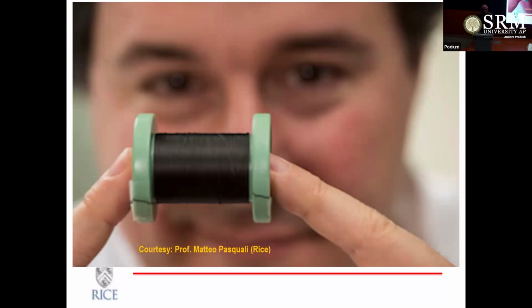So the only issue with carbon nanotube is it's too tiny, right? It's about 1 or 2 nanometers in diameter and maybe microns long. But you can't really use a nanotube that is a few microns long as a fiber for any practical applications. So in order to get to that point where you can actually use these nanotube building blocks as a fiber, you need to put them together. You need to engineer them into a real fiber that you can practically use, like a carbon fiber. Now, it has taken almost 30 years, and we still don't have a fiber that is as good as the present carbon fiber, which is made by extrusion and so on, right?